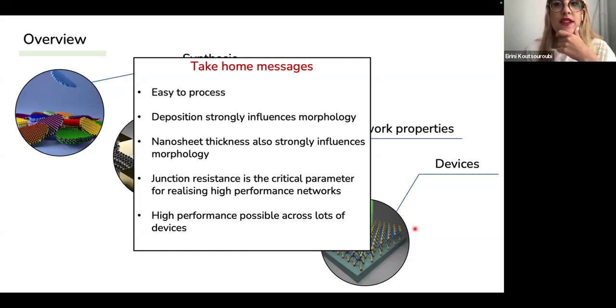Are there any assumptions for the drastic jump in conductivity? Well, the reason for these jumps in conductivity, some of the ones that I showed, are typically percolation effects. So the dominant effect here is going to be the thickness of the network. And what we find is that, once you're in the percolation regime, it depends then on the thickness of the particles themselves. And this is the characteristic that you want to control then to modulate your conductivity over orders of magnitude in the percolation regime. So again, nanosheet thickness would be the factor that you'd want to consider there.